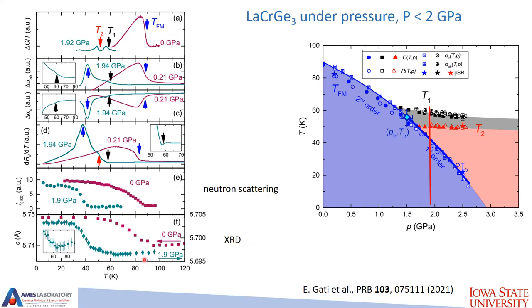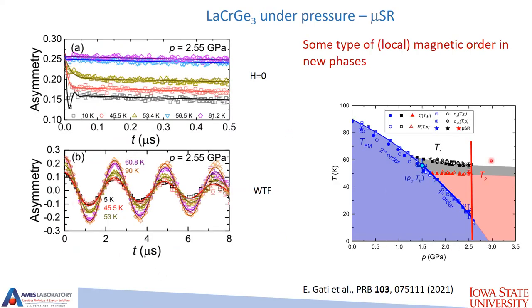And in X-ray, which is basically a thermal expansion, you see the ferromagnetic transition. And for 1.9 GPa, you probably see T1, it's beyond the error bars. Excellent. If you do muons, and this time we decided to do them at higher pressure so that we are sure that we are in the state where there is a new phase, you can again detect some kind of magnetic order.